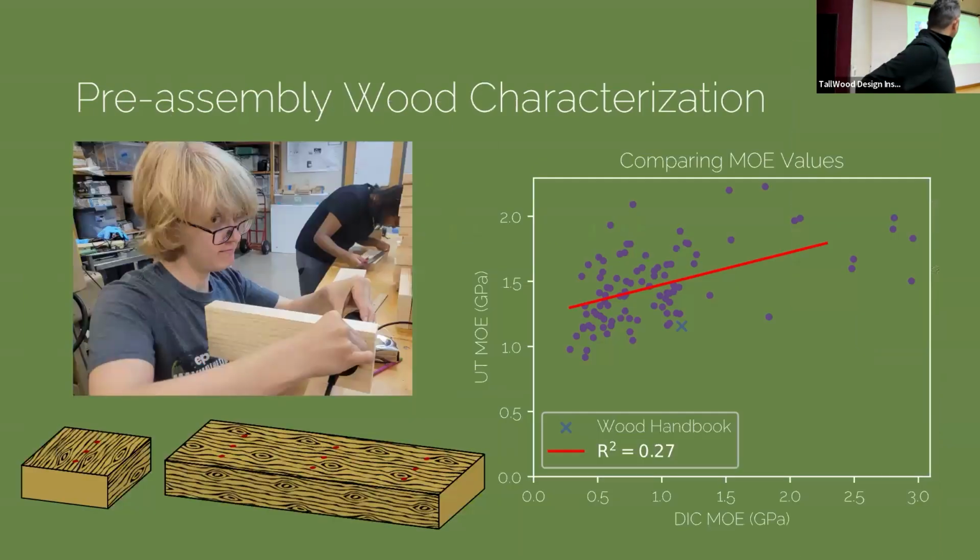With that, we started working, and here there is a huge synergy with the project. Lech is leading the study of the impact of thickness tolerance and thickness variation on the bond integrity of CLT. So we scan all the wood samples for a small CLT fabrication and compare the modulus of elasticity from the ultrasound data with that measured by Lech's team using the DIC method.